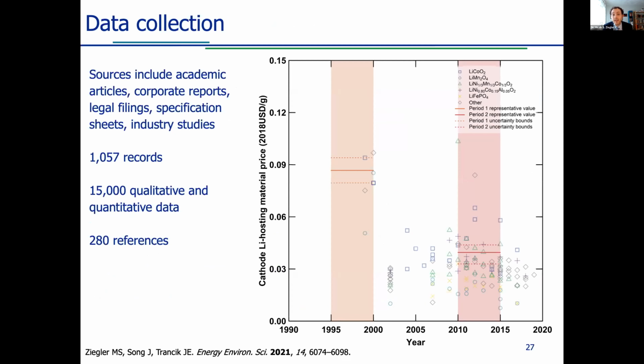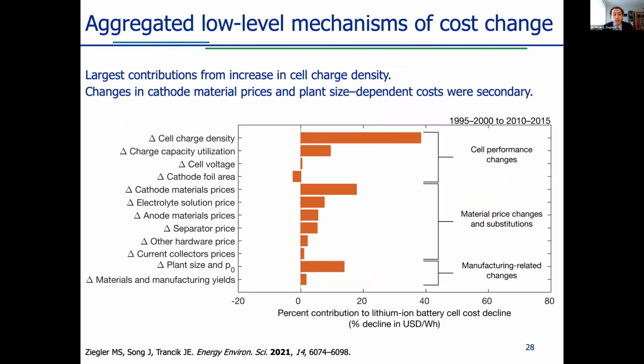On the right here, I've plotted the data we collected for just one of the 41 variables, the price of the metal oxide material in the cathode. And you might note I've highlighted 2 time periods in this plot of price data. These are the periods between which we're going to compare cost change. We're going to compare a representative battery cell from the 1990s to a representative cell from the early 2010s. Within each period, we develop a representative value for each variable, which I plotted here as horizontal lines. We also estimate the data uncertainty for each variable, plotted as the dashed lines above and below the representative values. Given these data and similar data for the other 40 variables, we can quantify the contributions of the low-level mechanisms of cost change. I've aggregated some of those contributions and plotted the results here.